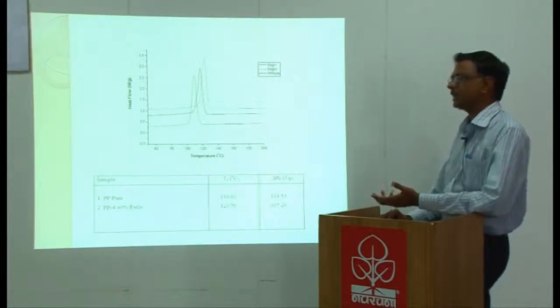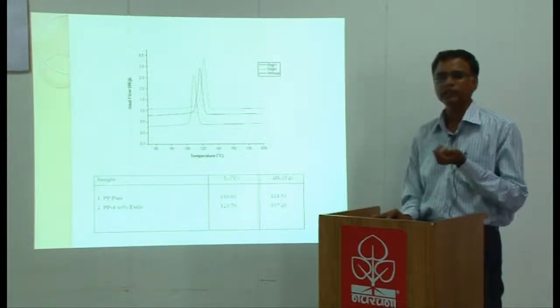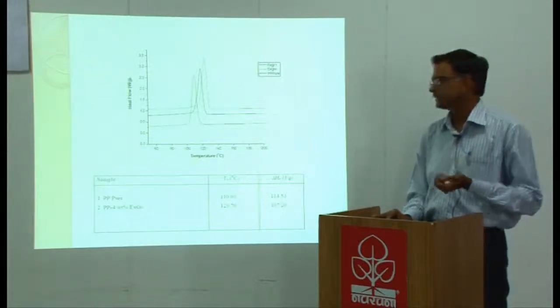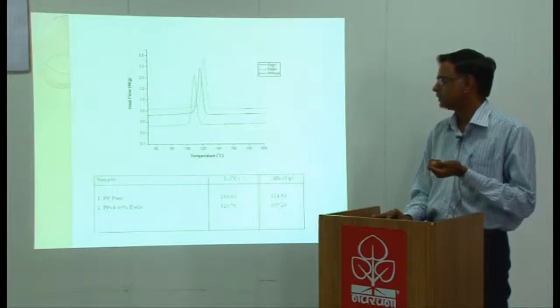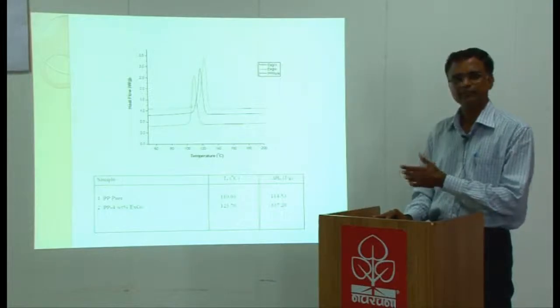What it means is that these expanded graphite nanosheets act as nucleating agents so that they try to induce crystallization of PP at higher temperature itself.